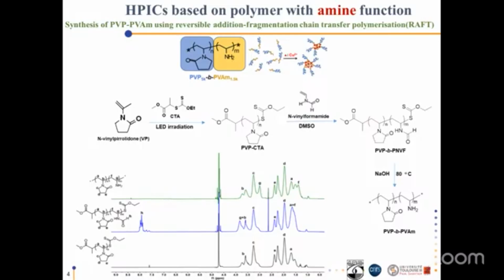Next, please. In the present study, we investigate colloidal structures based on hybrid polyion complexes formed by the complexation of copper ions with a double hydrophilic block polymer comprising a neutral polyvinylpyrrolidone block and an ionizable polyvinylamine block, PVP-PVAm. You can see this scheme of complex formation. And we evaluate the ability of the mentioned HPICs to promote a synergetic effect in O2 activation reactions.